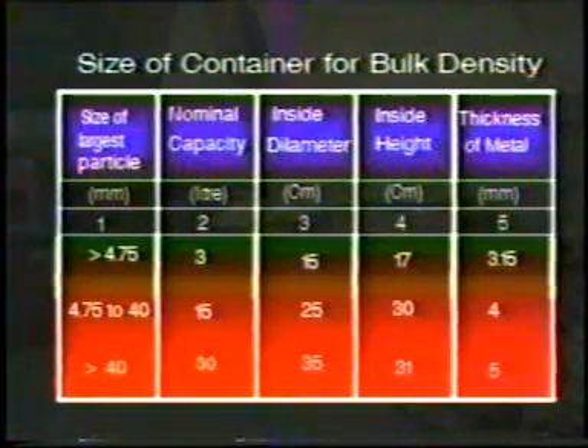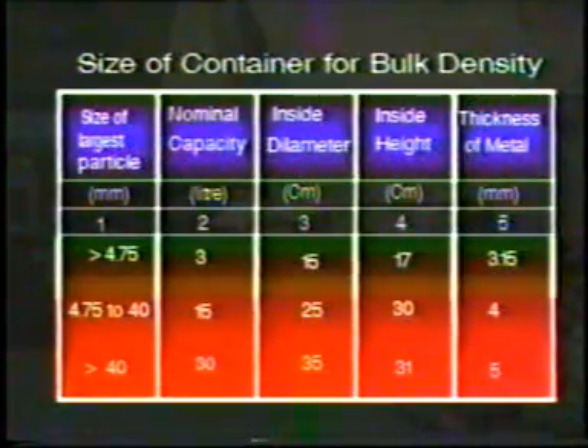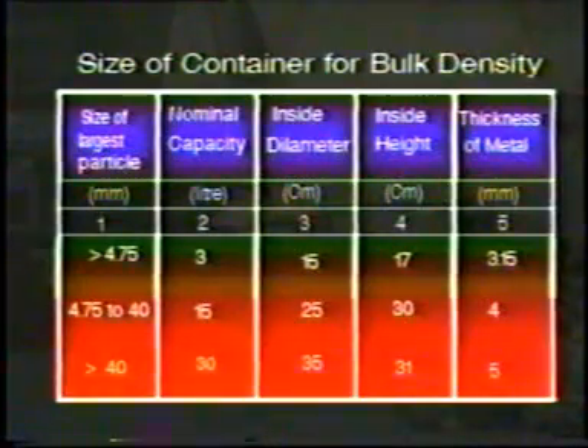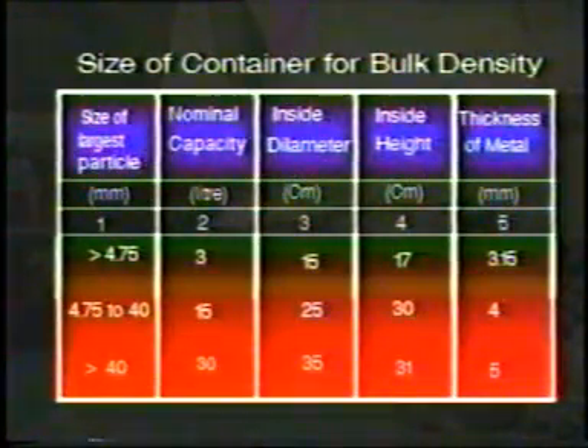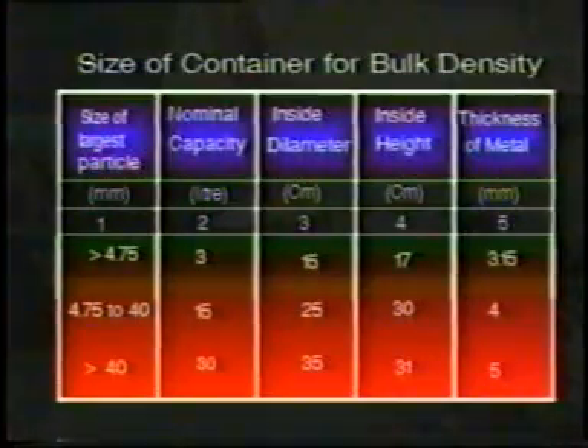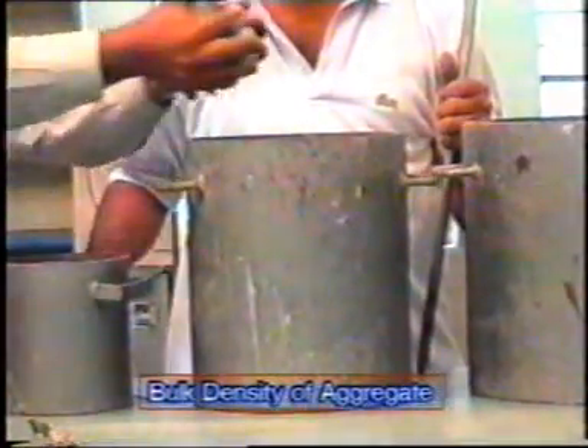As you can see in the table, the sample now selected passes through the 40 mm sieve and is retained on the 4.75 mm sieve. The corresponding metal measure for determination of bulk density is 15 liter capacity, whose inside diameter is 25 cm and whose inside height is 30 cm. Thickness of wall of the measure is 4 mm. Now this metal measure is selected.